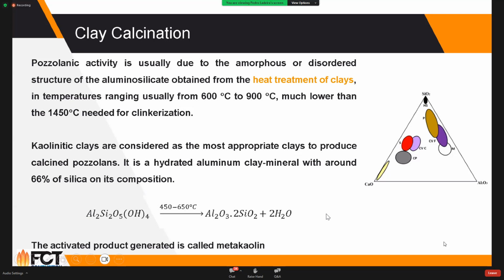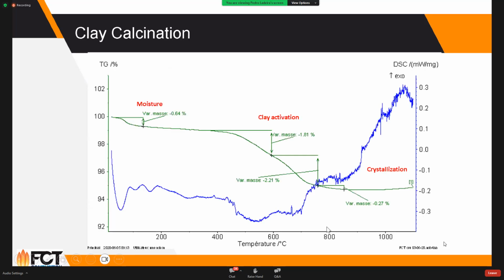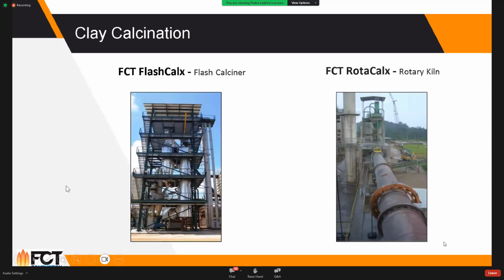Now, what we typically do, we map the material, we see where it loses moisture, when we activate the clay, and where it starts to crystallize. We'd like to have material that is pretty much amorphous. We don't like it to be crystallized, so we should reach a temperature where all the activation takes place, but then we stop it at a certain temperature to prevent the material from crystallizing.